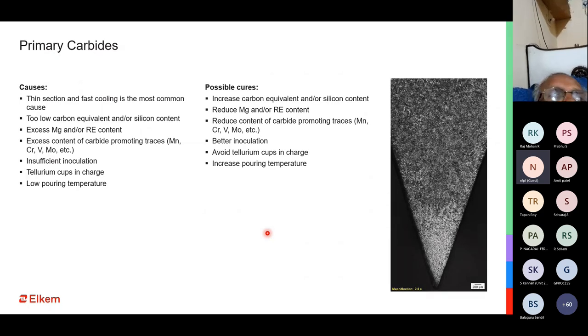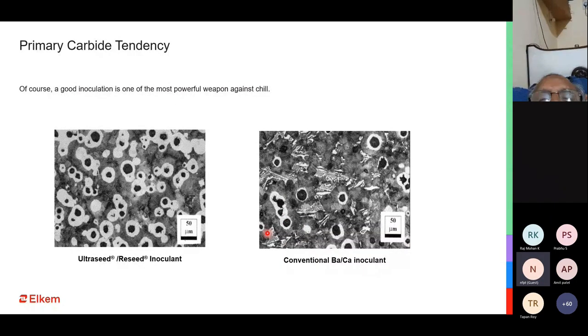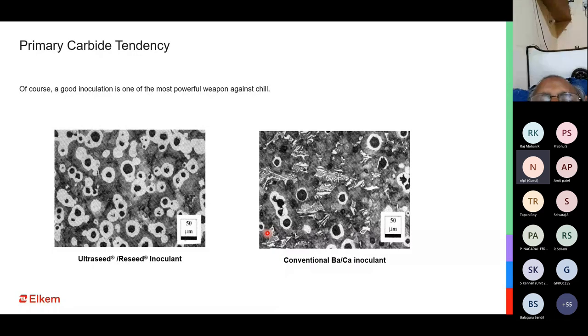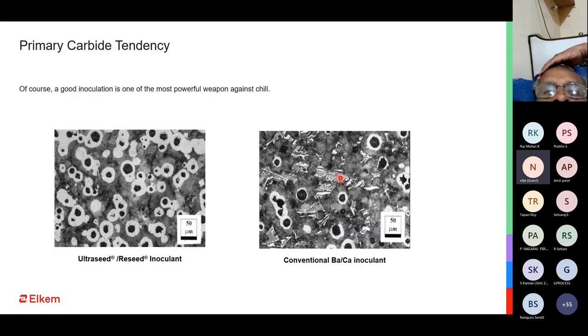For example, we do not want any trace elements coming into the system. Of course, we have to avoid tellurium cups going back into the furnace, and we have to make sure our temperature is optimum for the kind of casting that you're manufacturing. Of course, good inoculation is one of the most powerful weapons against chill. You can see it here. We have seen cases where a high potent inoculant is able to control the carbide and chill forming tendency, compared to a low potent barium, calcium or calcium based ferrosilicon based inoculant which is giving you carbides.